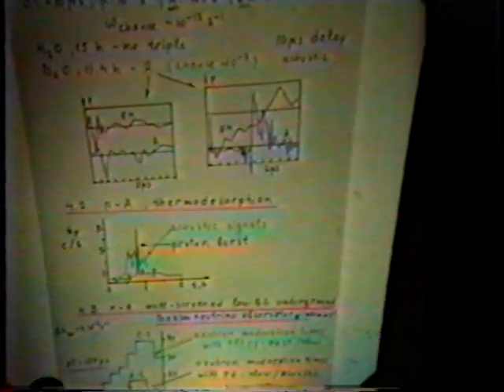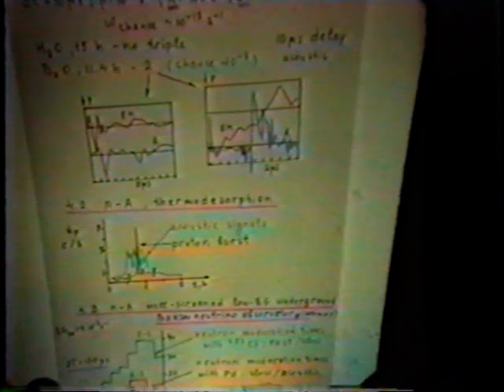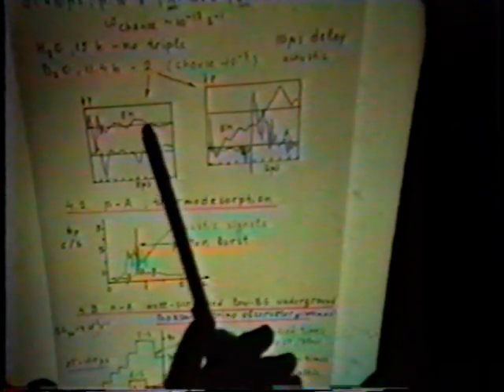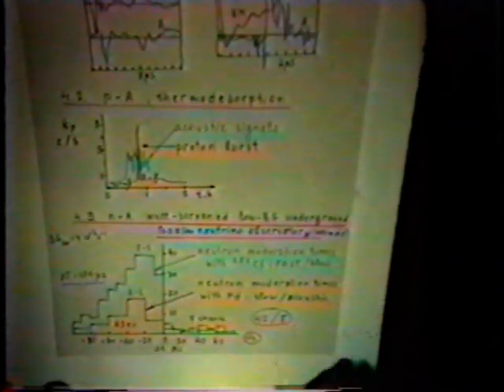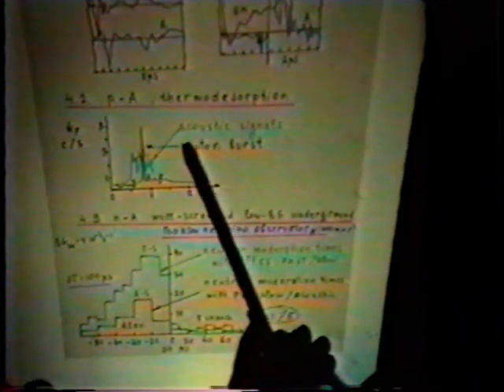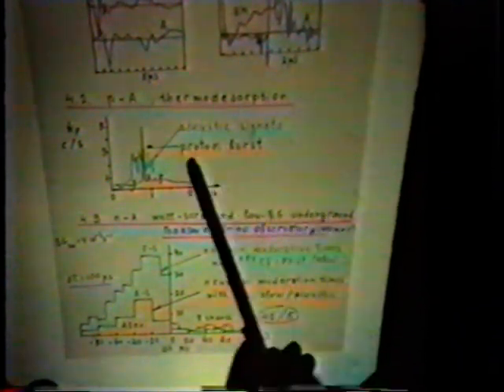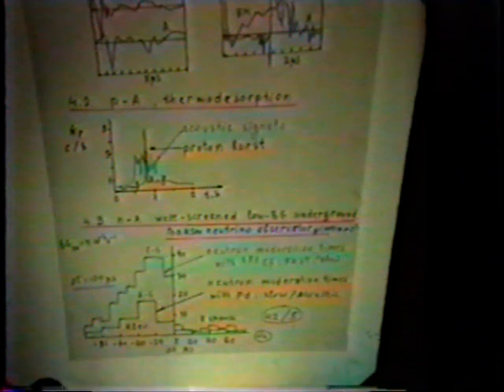During the main run with electrolysis of heavy water for 11 hours, they observed two triple correlations, and their oscillograms are schematically shown here. The probability of chance coincidences was about 10 to the minus 7. Another correlation was recorded during thermal desorption between a proton burst and an acoustic signal.